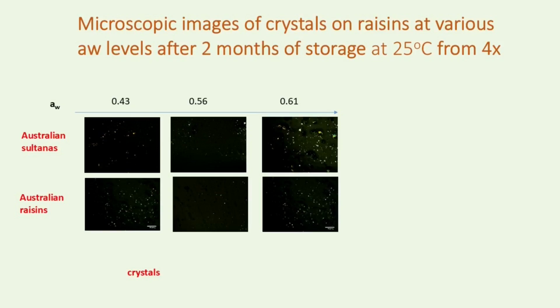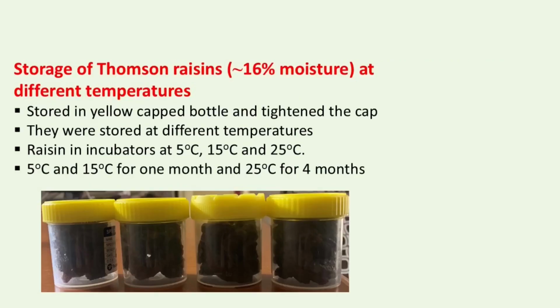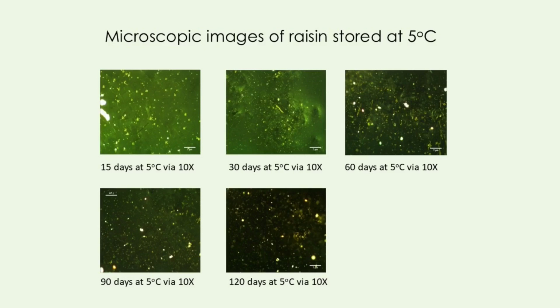A similar sort of thing we can do with the raisins as well. We put the raisins at different temperatures, 5, 15, and 25 degrees Celsius, and observed the crystallization. In all the cases, whether it is 5 or 15, we saw the crystals growing. But in some cases it's not visible, and in some cases it's visible. Even if the crystals are there, they are not growing, or there are a large number of crystals at lower temperature and they are not growing into bigger crystals. So there is no change happening on the surface in some cases, depending on the temperature condition.